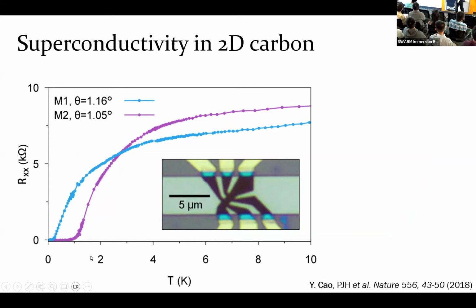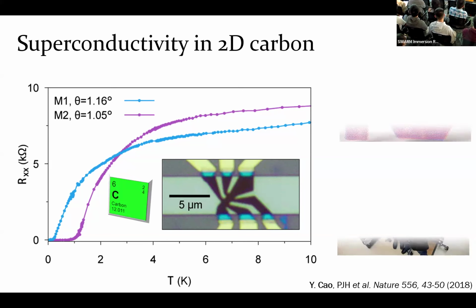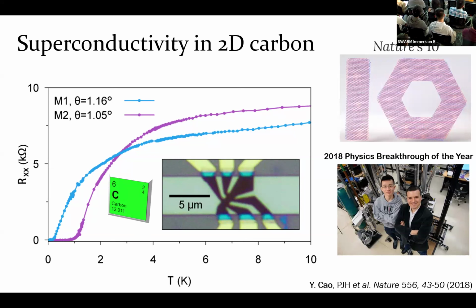For example, these occur at really low temperatures, like this is 2 kelvins. But below that temperature, the resistivity becomes absolutely zero, and you can measure that just by measuring the four-pole resistance of this device. And again, this is really astonishing because in carbon, or any form of carbon, including the 2D form of carbon, which is graphene, superconductivity has never been observed before this. So we're really creating this new phase of matter just by twisting, and that's why it was a pretty shocking discovery at the time in about 2018 during my PhD.